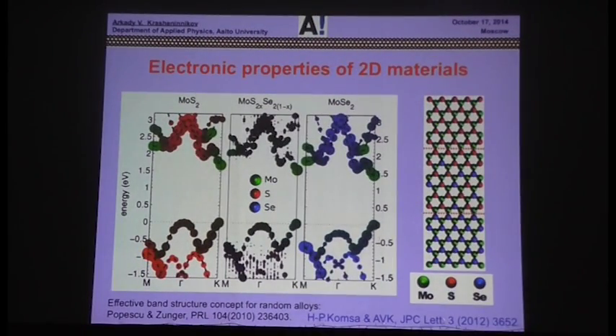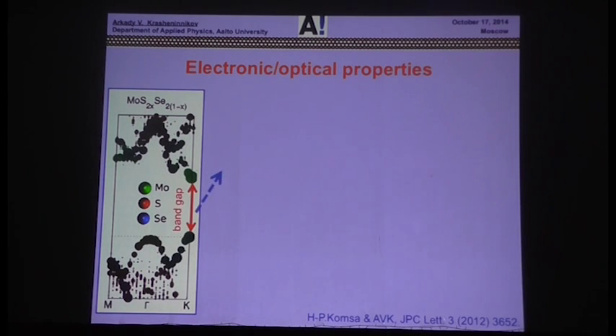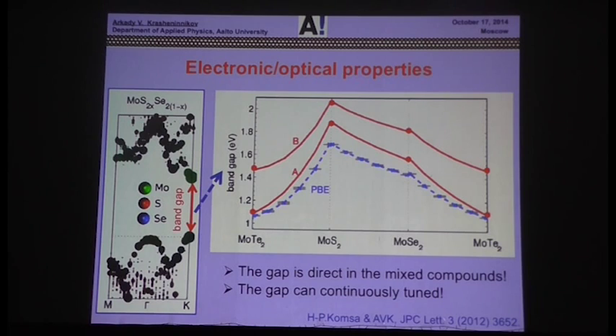And we used the so-called effective band structure approach to calculate electronic properties of these random alloys. It's a bit counterintuitive because the system doesn't have periodicity, but what's important is that the crystal structure is more or less the same. The changes in the unit cell size for mixed materials and for original materials are very, very small. So you can essentially calculate the electronic properties of a big supercell and then project it back to the primitive cell and calculate the electronic band structure. The upshot is that the gap remains direct, and what's important, it can be tuned continuously depending on the composition, basically from 100% sulfur to 100% selenium, it will decrease.